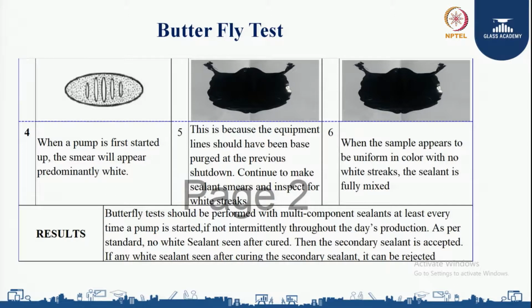The result: the butterfly test should be performed with multi-component sealants at least every time a pump is started, if not intermittently throughout the day's production. As per the standard, if no white sealant is seen after curing, the secondary sealant is accepted. If any white sealant is seen after curing, the secondary sealant is rejected.